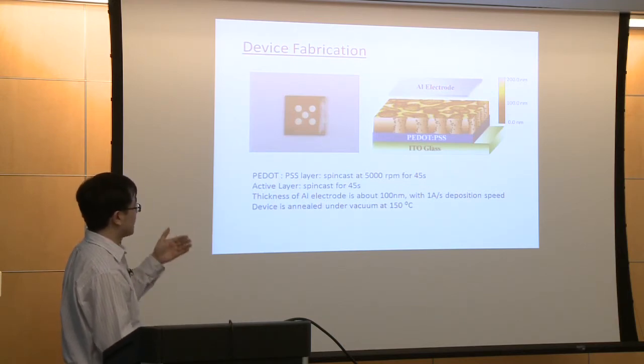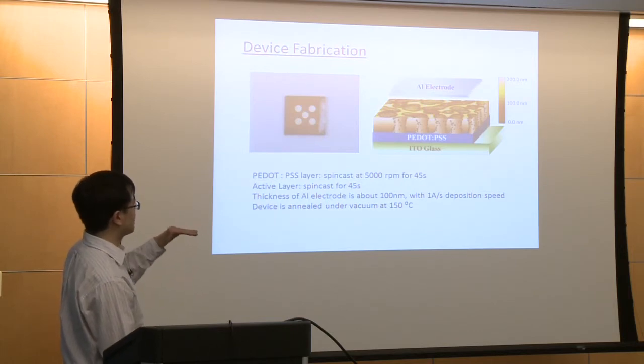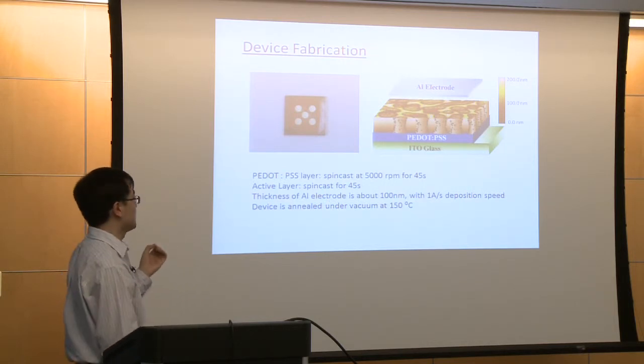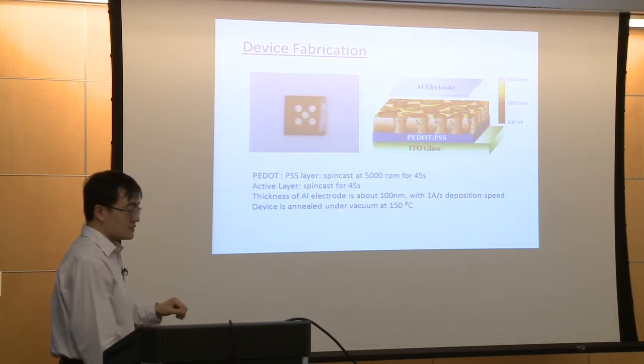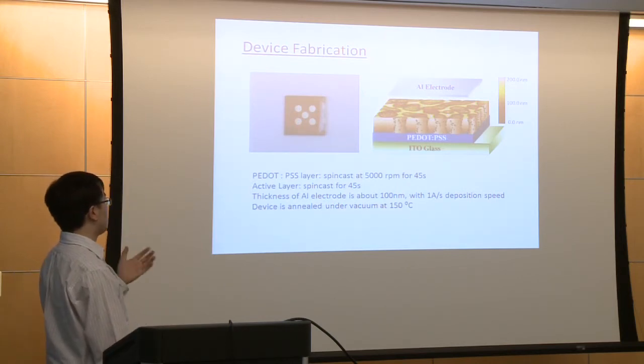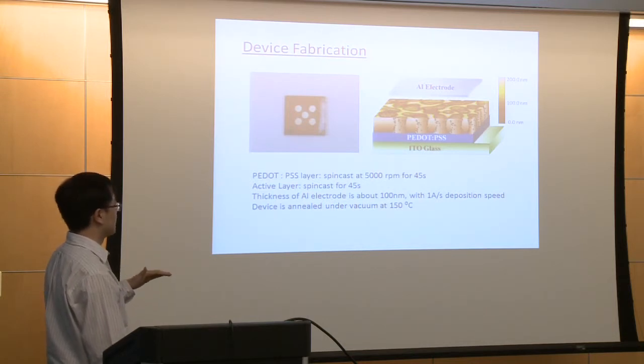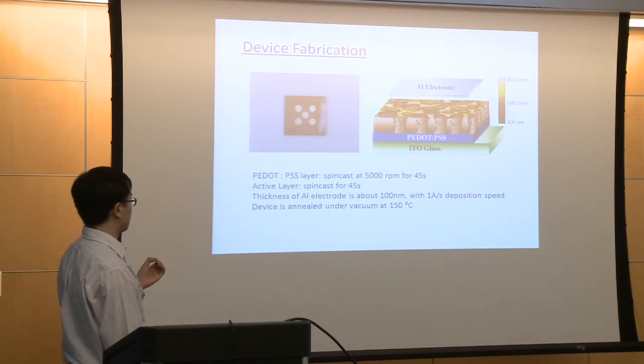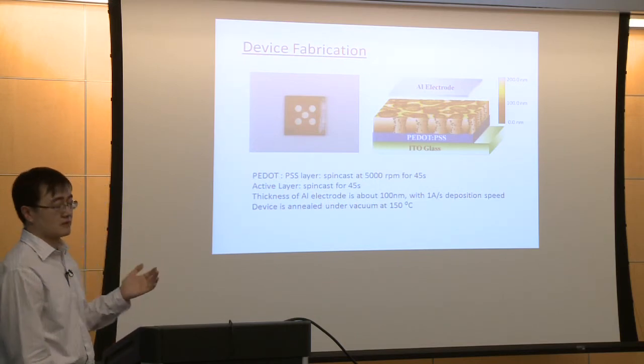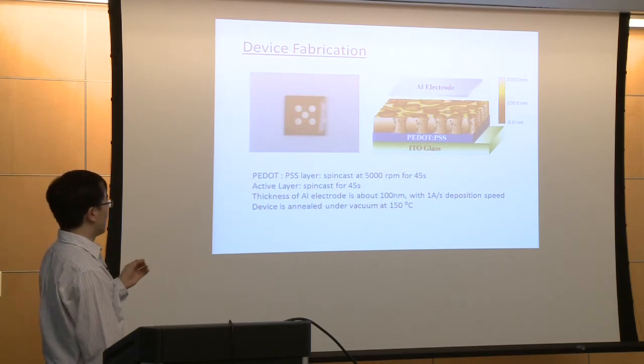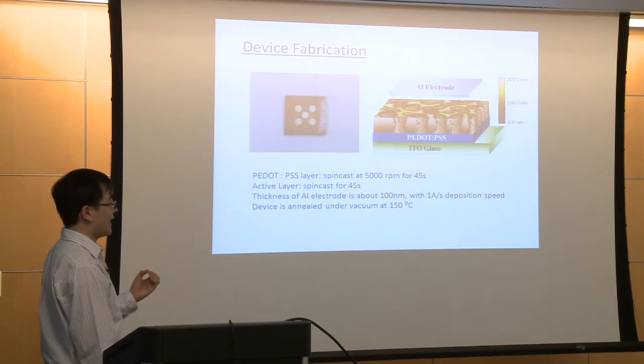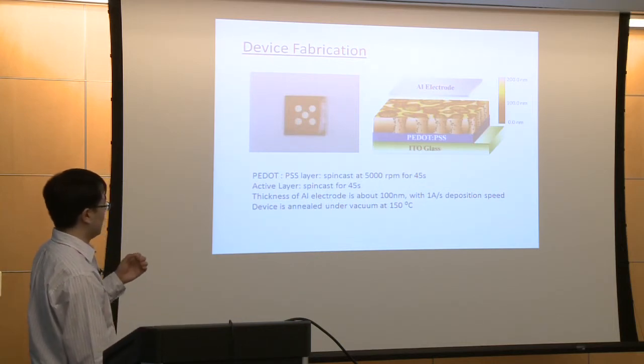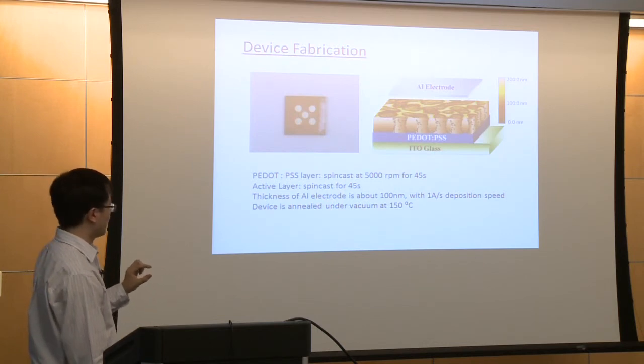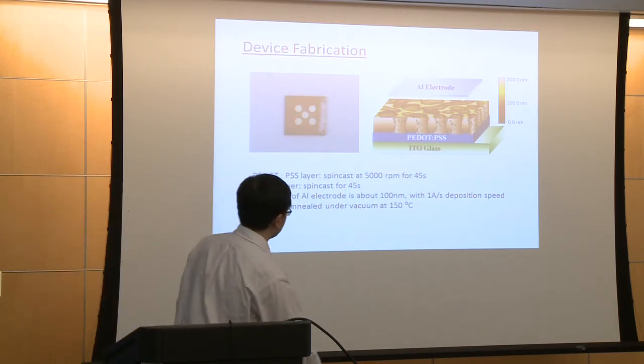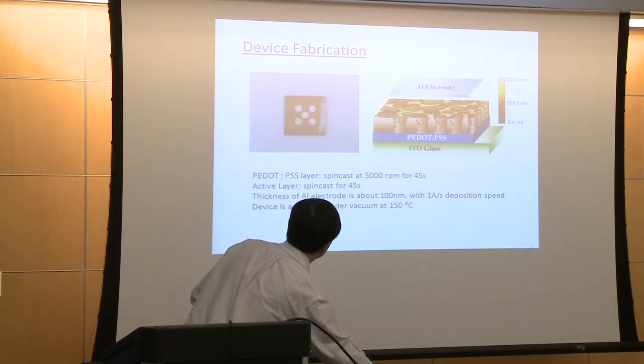The right image is the cross-section picture of our device. There's ITO glass, PEDOT:PSS layer, then our column structure made of P3HT, polystyrene, and PCBM, and then the aluminum electrode. We made our device by first spin casting the PEDOT:PSS layer on the glass substrate at 5,000 RPM for 45 seconds. Then we spin cast the active layer at about 700 RPM for 45 seconds. Then we deposit the aluminum electrodes at about 1 angstrom per second until the thickness of the aluminum reaches 100 nanometers. Then we anneal the whole system at 150 degrees C in vacuum.